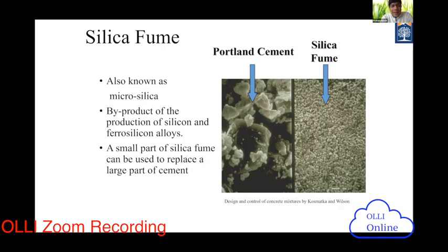So we see that it is microsilica. How fine is this material? This material is 100 times finer than a cement particle. So you see the cement particle, how big it is compared to silica fume, how small they are. Just to give you an idea, silica fume surface area is 20,000 square meters per kilogram, whereas tobacco smoke surface area is 10,000 square meters per kilogram. So now you can imagine how fine this silica fume material is.